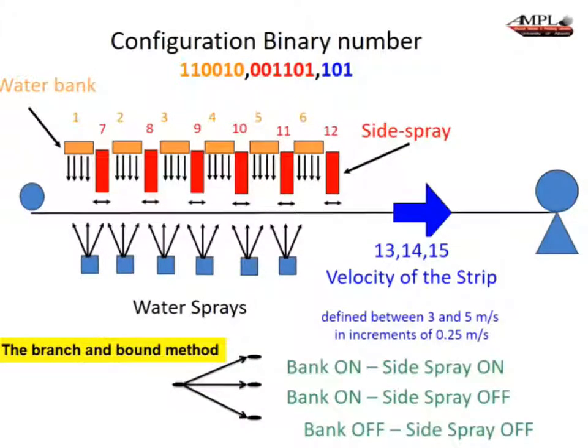I won't go through this in too much detail, just in the interest of time, but here are, for example, the various banks, 1, 2, 3, 4, 5, 6, and the side banks are 7 to 12. And essentially, for something like this, you can't just use a simplex search. You have to basically discretize these steps. And so when a 1 appears here in the first set of digits, it means that particular bank is on. In the red digits, it means whether the side spray is on or not. And the 101 represents the velocity of the strip, which we use 3 digits to represent. The velocity of the strip ranges from 3 to 5 meters per second in increments of 0.25.